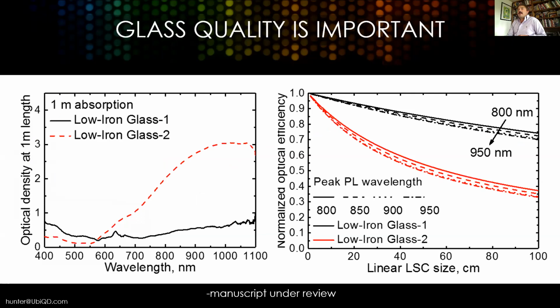Now, as you can imagine, having all of this glass there as a waveguide makes the glass very important as well. So the quality of the glass is critical, and also for the aesthetics. Normally, a better quality glass would mean a more clear glass. A lower quality glass might be a little bit greenish, which is common, and that's due to iron absorption in the glass. Iron is added through the float process to make it manufacturable. But you can purchase low iron or even no iron float glass nowadays. Even within those categories, there are widely varying properties. It's just showing here that one low iron float glass is not equivalent to another, which has a big effect on the performance. It could be a 50% difference as you scale up to a square meter, and how the quality of that glass plays a role. Again, this will be in the manuscript that's about to be released.